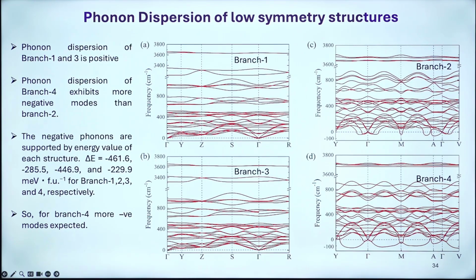So this is like a group-subgroup transformation. I am trying to search from one space group by slowly moving the atoms with the displacive transformation. Branch 1 and 3 are giving the minimum. Yes, yes. And then branch 2 and branch 4, although I have a new space group, I am not going to get any benefit out of it. So I am ruling out that possibility, and our interest is to see whether we can get a decent polarization which is sizable and non-zero, from branch 1 and branch 3.